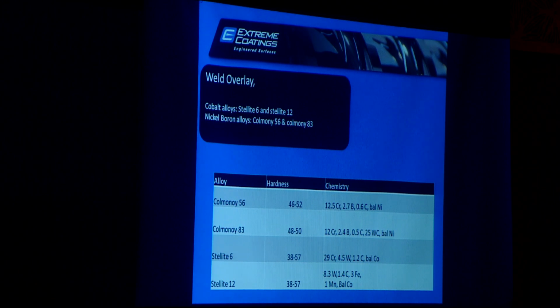Sometimes people ask me, the bimetallic from China is cheaper, from Europe it is costly, and this and that. The idea is people are not aware of what they are buying. So there are basically four kinds of welding material people use. There are Colmonoy 56, Colmonoy 83, Stellite 6, and Stellite 12. And you can see the chemistry of it on the right-hand side. The very best available was Colmonoy 83. Why? Because it had up to 25% of tungsten carbides. It can go up to 30-32% also, depending on the suppliers.